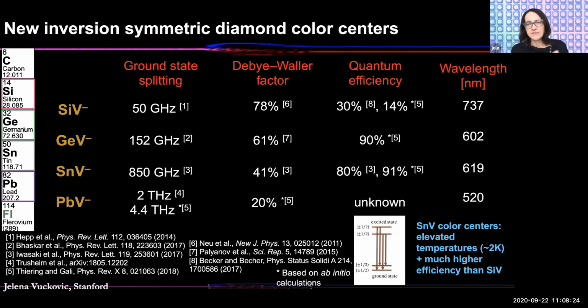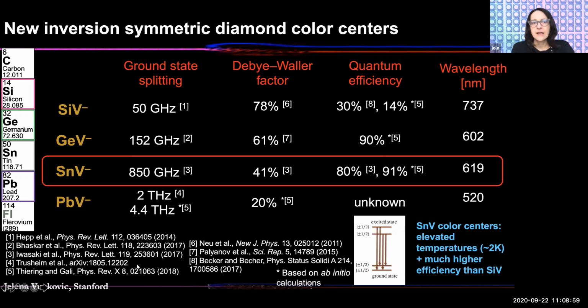There has been a lot of activity over the past several years on silicon vacancy color centers in diamond. All of these centers are basically produced by removing 2 carbon atoms in diamond and inserting 1 extra interstitial impurity in between these 2 vacancies. So most of the effort has been on silicon vacancies over the past several years. You may have seen a lot of exciting work in that space. We've also done a lot of work on silicon vacancies, but at the moment, we're primarily interested in tin vacancy